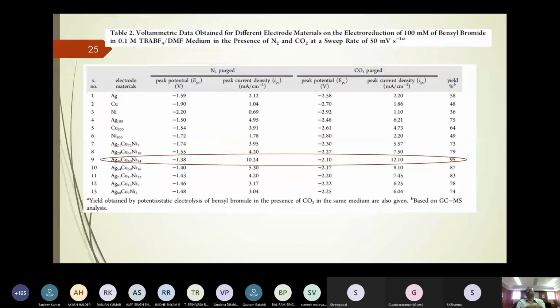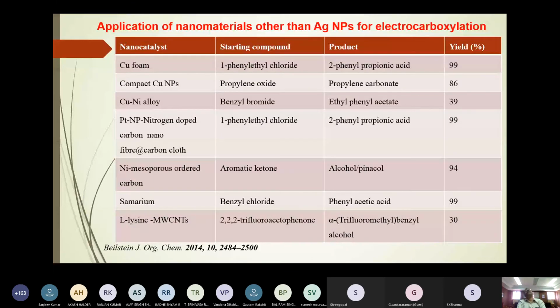Okay. Now this table shows the conversion of benzyl bromide to phenylacetic acid using many materials: silver, copper, nickel planar electrodes, pure nanomaterials, and silver copper nickel alloy. Among these, silver 46, copper 40, nickel 14 shows the highest yield of 95%, with a low potential and high current, both in the absence and presence of CO2. Okay.